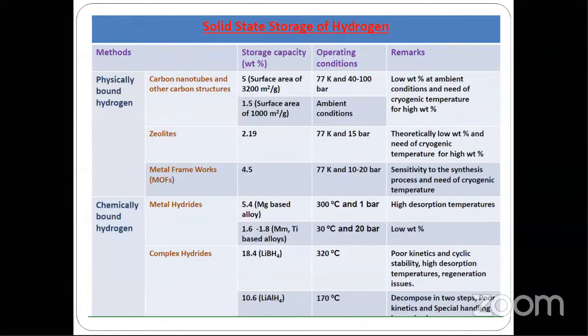Again, if you see the carbon nanotubes, even though it's going with 5%, the problem is the low temperature. You have to operate this storage tank at 77 kelvin, and the pressure is again 40 to 100 bar. Again, these are deviating from our DOE target. So the need of cryogenic temperature for high weight percentage is the drawback for these carbon based materials.